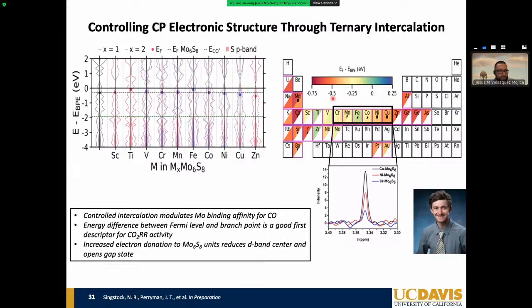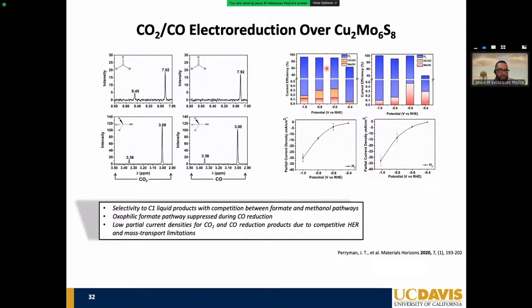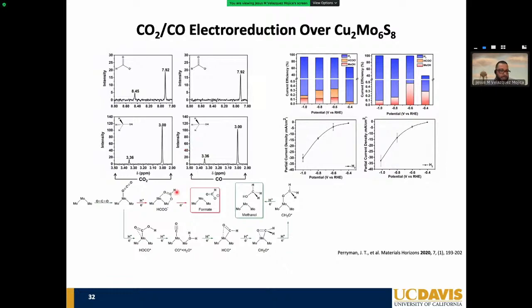So now we are in that process, as you could see here from the CO2 characterization to control reactivity. Something really interesting was elucidated through the electrochemistry here. What I'm showing you here is the reduction of CO2. If you look at the gaseous product, there's a lot of production of hydrogen. However, when you only focus on the liquid phase, you see only the presence of methanol and formate. However, when you switch from CO2 to carbon monoxide, you only see the production of methanol in the liquid phase. That is really exciting because what it's hinting is that potentially we are circumventing the oxophilic pathway towards the production of formate, to instead favor the carbophilic pathway towards the production of methanol.